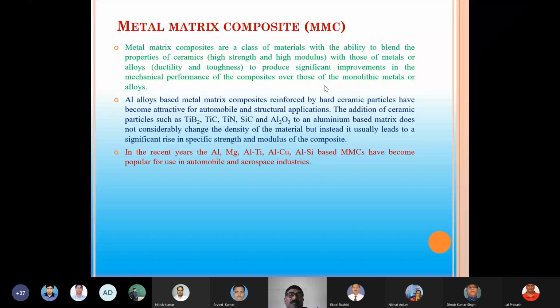Aluminum alloy based metal matrix composites reinforced by hard ceramic particles have become attractive for automobile and structural applications. The addition of ceramic particles such as titanium borides, titanium carbide, titanium nitrides, silicon carbides, and aluminum oxides to an aluminum based matrix does not considerably change the density of the materials, but usually leads to a significant rise in the specific strength and the modulus of the composites.